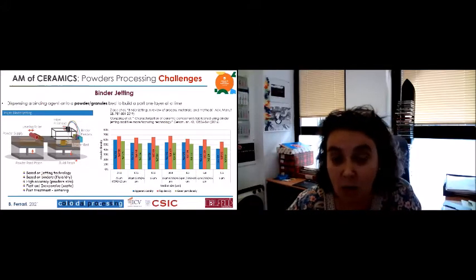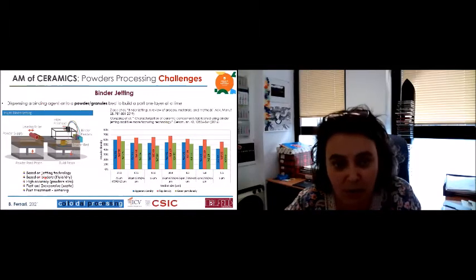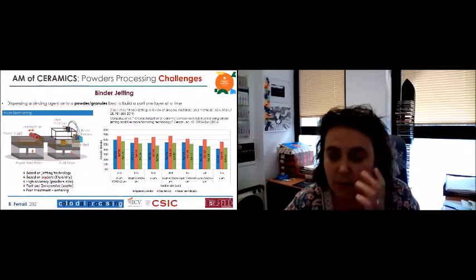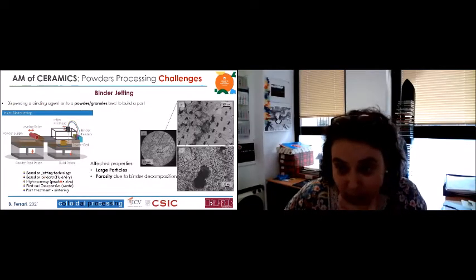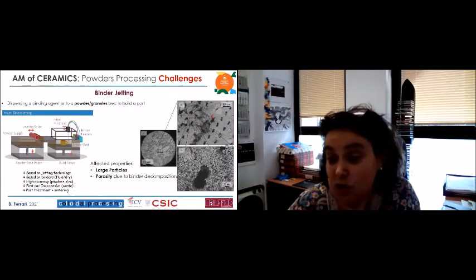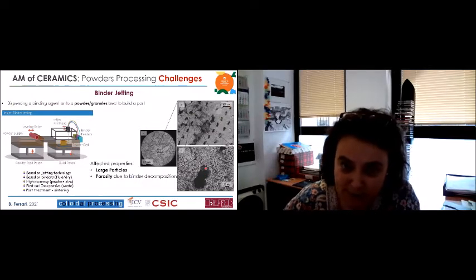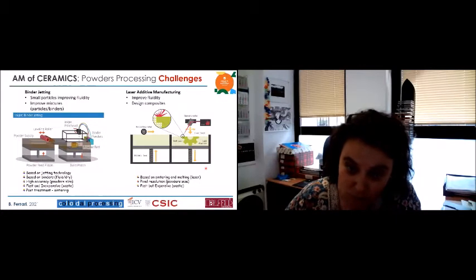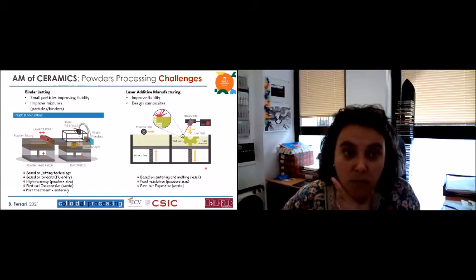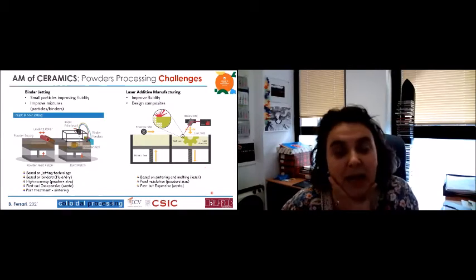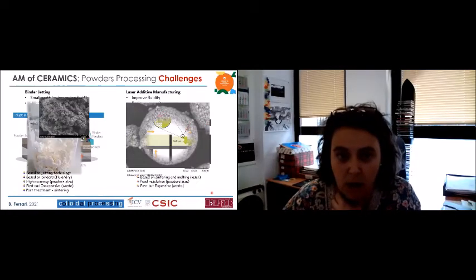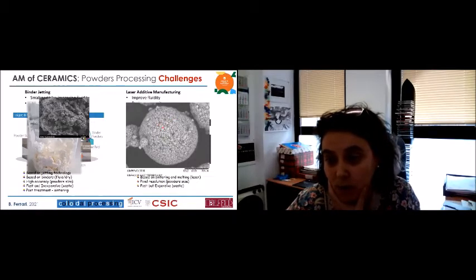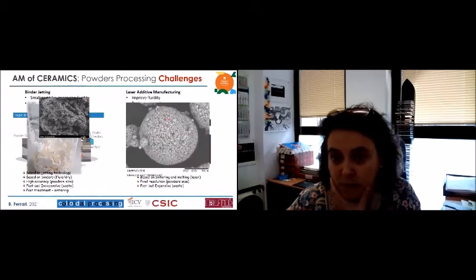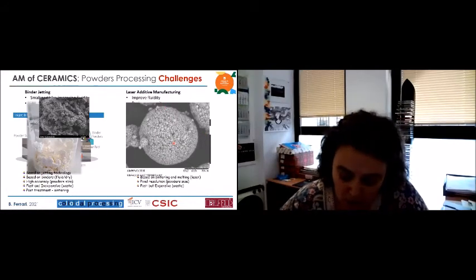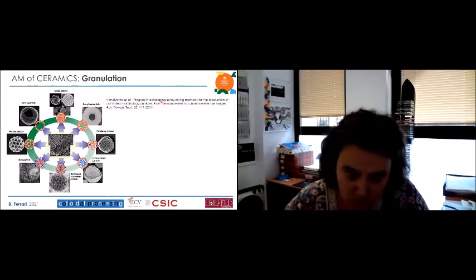Of course, this technology has a conventional thermal treatment after you have your part, and the amount of binder is very important here because you must remove the binder during the thermal sintering, right? So the problem of this binder is creating large porosities in the pieces that we need to avoid, to improve the characteristics of the properties of the powder. And one way to improve in both technologies the characteristics of this powder is to make granules, so that these small particles become a bigger one, and the fluidity of these particles increases with the size of the granules that you put in the bed, right?